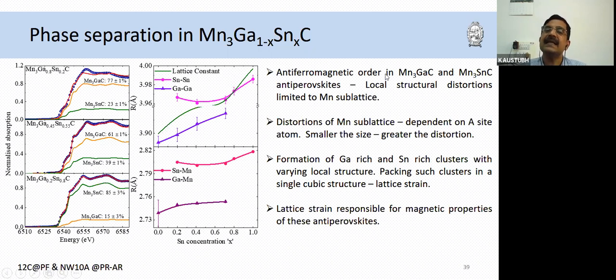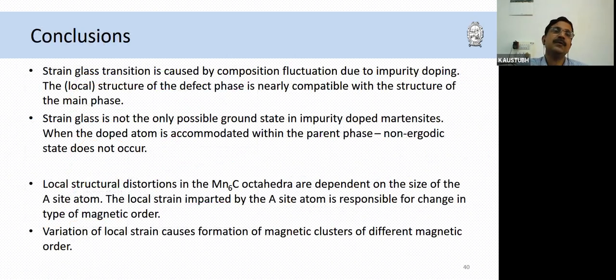So what we can say is that the antiferromagnetic order in these manganese antiperovskites is because of local structural distortion limited to the manganese sublattice. The distortion of the manganese sublattice probably depends on the size of the A-site atom. The smaller the size, the greater the distortion. And this leads to formation of gallium-rich and tin-rich clusters, and the packing of such clusters within the single cubic lattice causes some sort of lattice strain, and this lattice strain is responsible for the magnetic properties of these antiperovskites. So that brings me to the final conclusion of both the examples that I took.